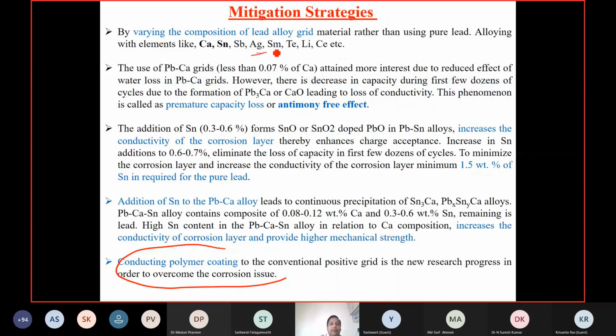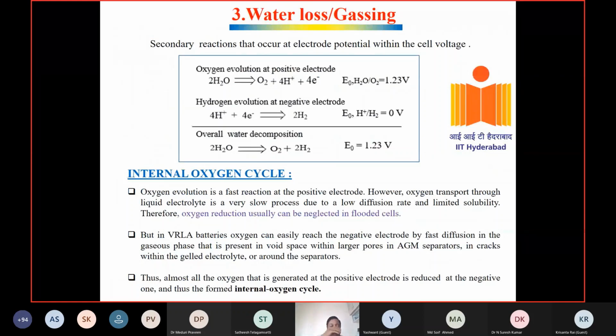Silver generally. Some people use tellurium, selenium. All these things are there, but mostly lead, calcium, tin, aluminum alloys are used. It's okay, but still not up to the mark. If you can have a good corrosion resistant grid along with reduced sulfation, it can improve the life of the battery. And water loss is another issue.